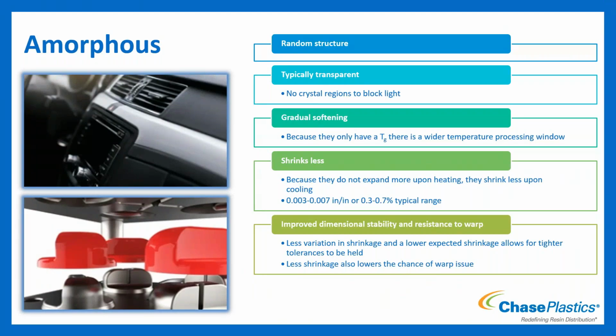The other thing to point out is I do provide some shrinkage values for these different materials. That's a general rule of thumb and a good starting point. But also remember, with shrinkage, there's things that will affect it, so it's not a hard and fast rule that that's the exact value. If you have multiple gates on your part, if you process it different than normal, the location of your gate - all of that can affect the shrinkage. So just keep that in mind when you see those values.